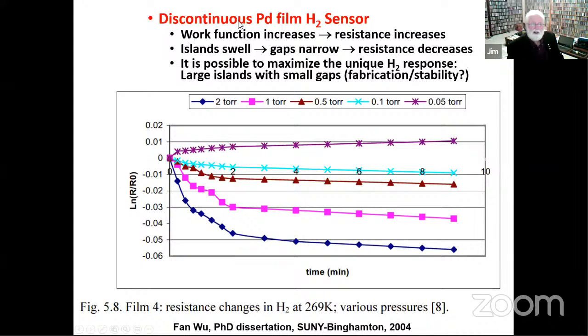But there's one combination, palladium and hydrogen. In palladium the work function will also increase, but the additional factor is that the hydrogen will go into the palladium islands and increase the lattice constant, increases the island size, so the gap narrows and the resistance decreases. So here we've got both effects at different pressures. At low pressure, there's only the surface effect and resistance increases. But as you have a greater concentration of hydrogen, then you get this negative effect.